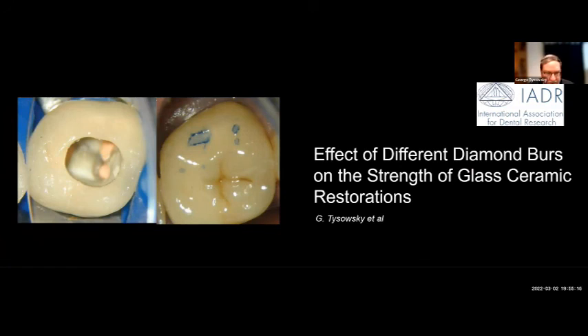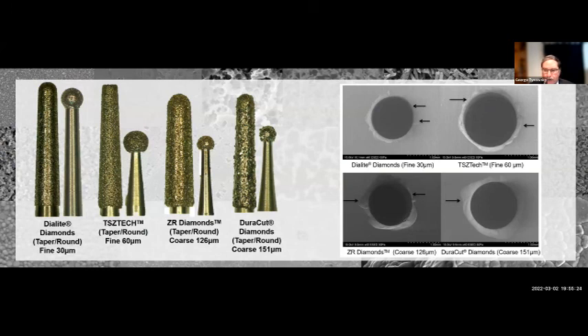So again, this is a study that we conducted a few years ago. It was published in the IADR annual session. If we have endo access, we did a study looking at different areas, and what came out was that the coarser the diamond, the more damage it created to the restoration. So basically, we want to use fine diamonds, high copious water spray, high speed to penetrate these areas.